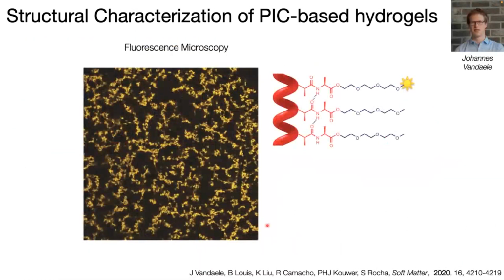Because it is a fully synthetic material, we are able to label it with a fluorescent molecule. So what we did was, on the side chain, we add the fluorophore, and then we just acquire some fluorescence microscopy. So this is just a Z plane of hydrogel that is labeled with the fluorophore. And then you see here the yellow are all the fibers, okay, and the black are the pores. And again, I keep forgetting to put the scale bars, but from here to here it will be around 20 micrometers, okay? These pores will be like 4 micrometers. They are very big pores.